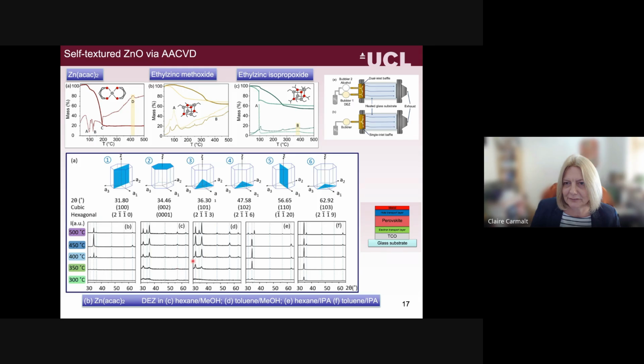Now, these two here are when you take diethyl zinc with methanol, so either with hexane as the solvent or with toluene. And then these are where you're using diethyl zinc with isopropanol, either in hexane or toluene. So you see you're getting very different XRDs that are forming. So for when you're using the methanol, you can see you're not getting that preferred orientation in the 002 plane. However, you are when you're using the ethyl zinc isopropoxide.